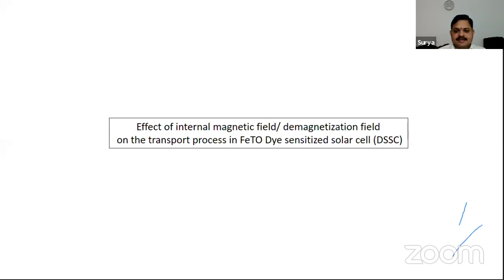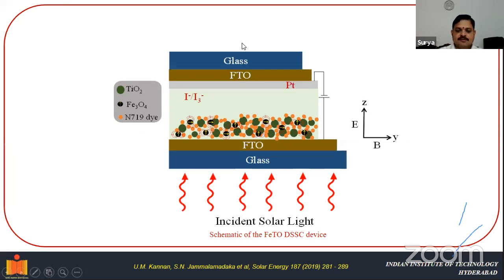The effect of internal magnetic field or demagnetization fields on the transport properties in Fe3O4 dye-sensitized solar cells. Okay, so this is the kind of device that we have developed. For instance, in addition to the titanium dioxide and dye, we also try to add the magnetic nanoparticles, which will have the stray fields around the nanoparticle. If you consider any permanent magnet, what will happen? From the north pole to south pole, there will be flux lines. Okay, so whatever rings that I have shown around the nanoparticle, they are basically going from the north pole to south pole. Individual nanoparticle will act like an individual magnet that leads to flux lines from north pole to south